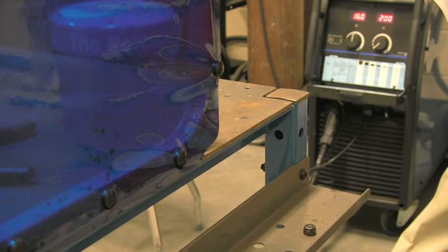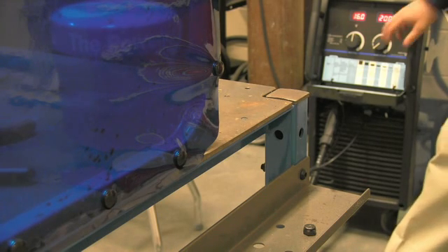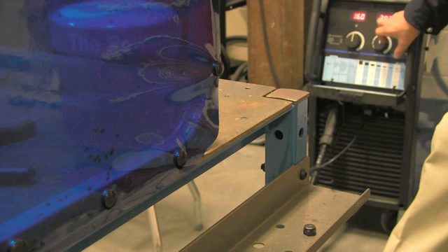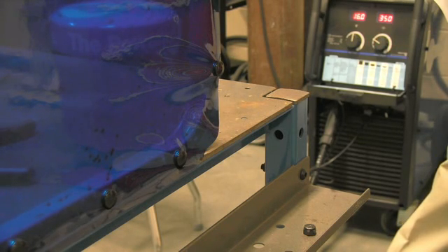So let's just say we increase the wire feed speed up to 350 inches per minute. So that's a pretty significant increase in wire feed speed, which will cause us to travel faster, which increases our productivity and our deposition rates. Now the question would be, well, where do we set the voltage? Well, we can certainly bet that we're going to have to increase the voltage since we increased the wire feed speed. So how much? Well, we'll have to see. Typically, I like to just increase it in 1 volt or even half volt increments until I get that stable short circuit sound that we saw earlier.